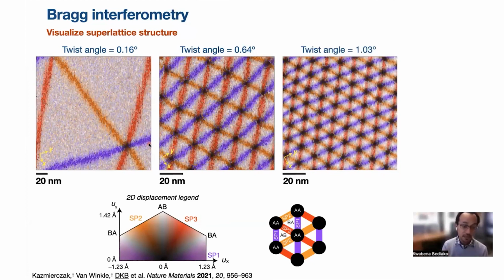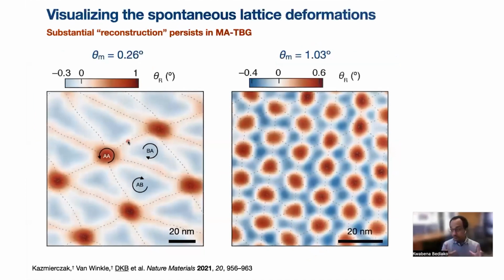But we can go a step further than that. Apart from just qualitatively visualizing this, because we have a displacement vector field, we can take the gradient of that displacement vector field and extract the 2D strain tensor field at each point in the sample. From that 2D strain tensor, we can determine the local rotations, the so-called rigid body rotations of our system. And if we then take into account the Moiré twist itself, we can get out the relaxation rotations, the rotations that are present in addition to the Moiré twist, and therefore the ones that are responsible for the relaxation process.